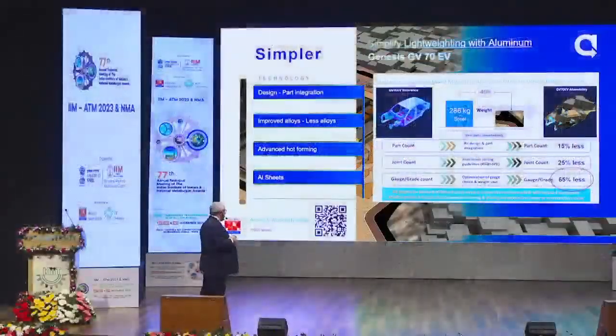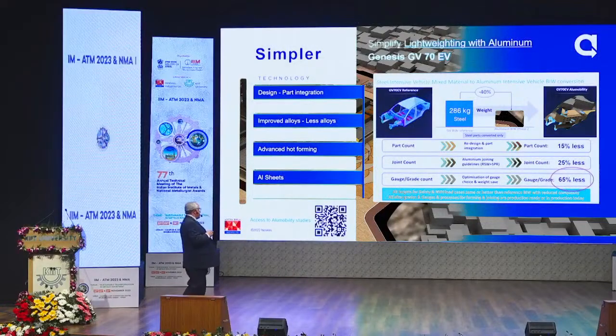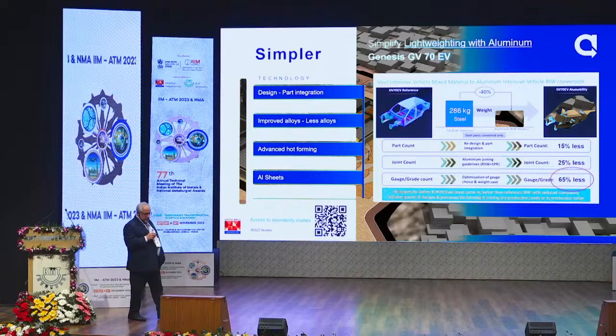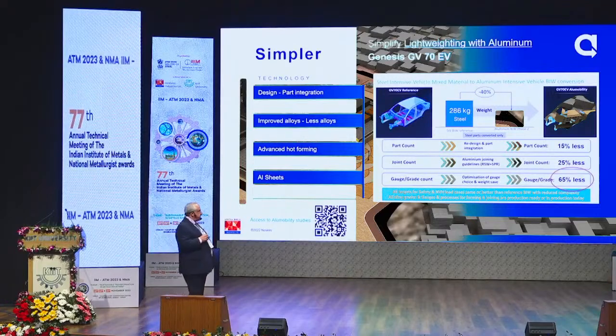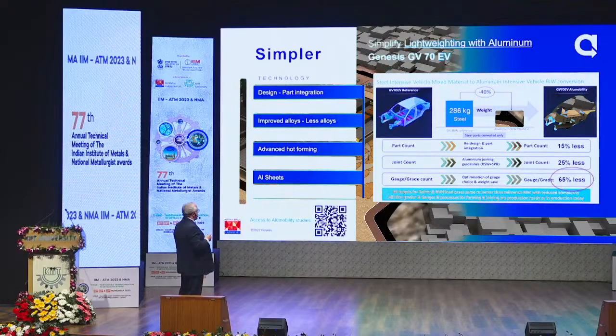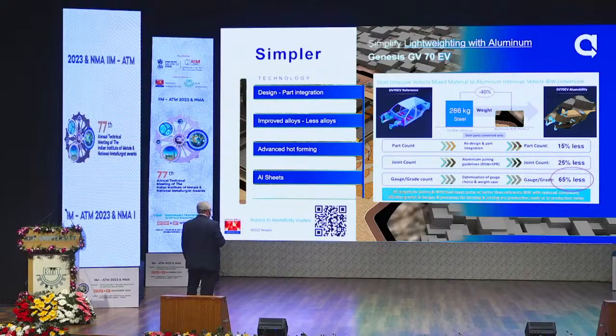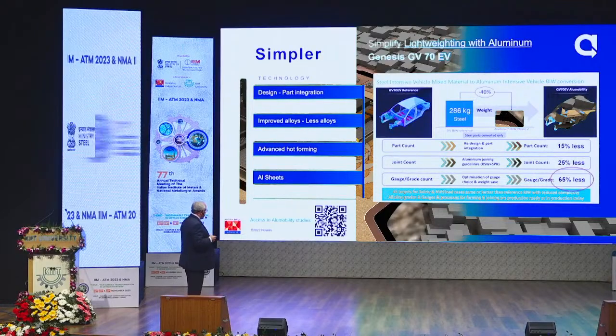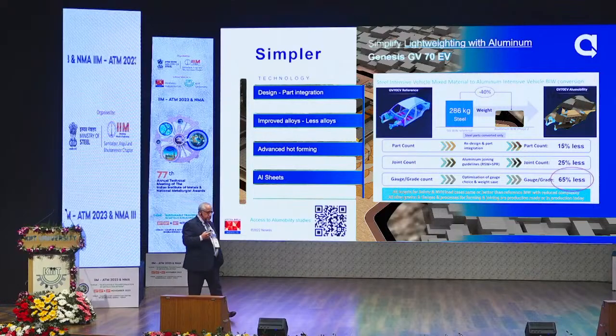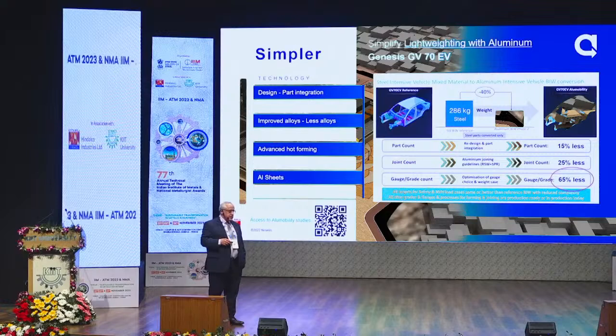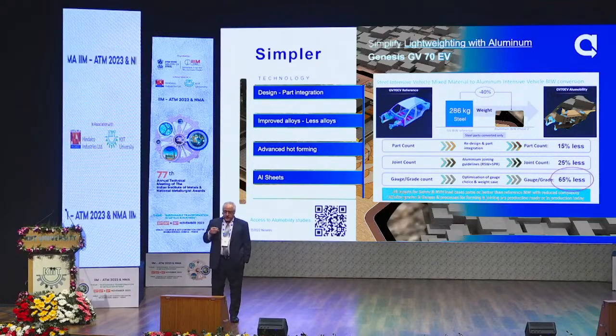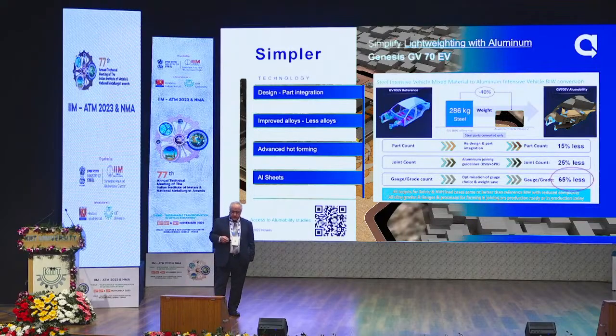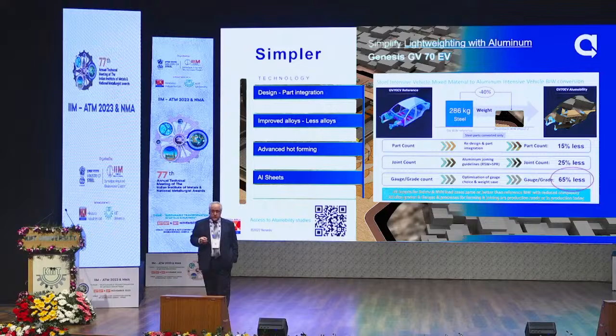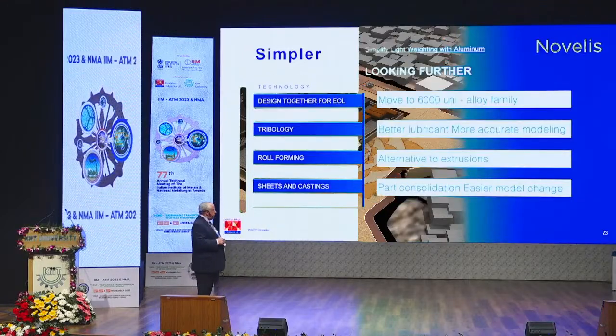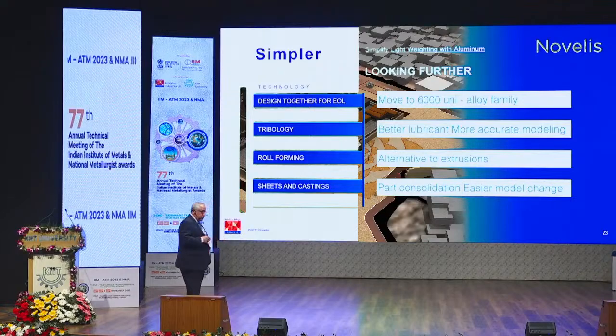And now coming to the last example, being simpler. Very nice study done with Genesis, with the people of Hyundai, showing that not only can we get the weight saving, looking now at a complete upper structure, again 40% weight saving, but also we can reduce the part count, the joint count, and even the combination of grades and thickness and heat treatment up to 65%. So this is done by improved design, simultaneous engineering, improved alloy selection, advanced hot forming, and aluminum sheets.